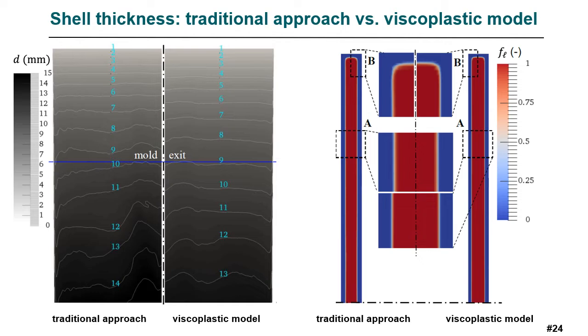When the viscoplastic model is employed, we observe more uniform solidification. However, shell growth also adapts to the flow oscillations and to the superheat redistribution. Application of the viscoplastic model in comparison to the traditional approach doesn't have such dramatic effect as electromagnetic braking against the case without magnetic field applied.